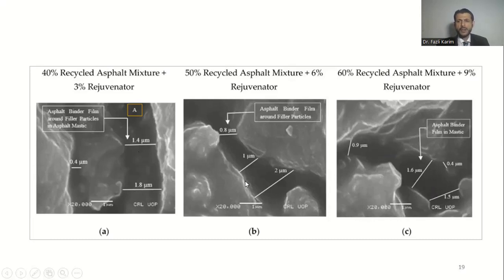All these images are almost in the same range, but one thing has been observed: the film thickness measured in the recycled mixture is a bit smaller than the film thickness measured in the conventional mixture, and it's because of the aging process, because the aged material was collected from a road which had already survived for 15 years. So that's why the film thickness is a bit smaller than conventional.